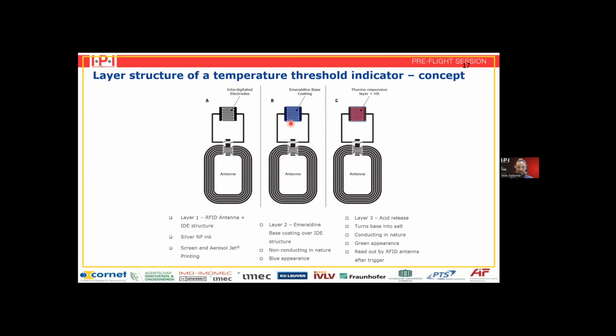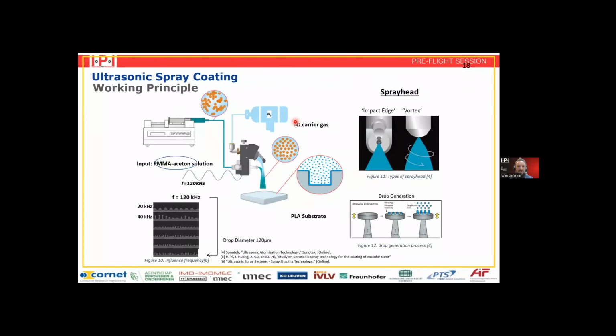And the coating itself is not screen printed, but is ultrasonically spray coated. That's a technology that we also have in the lab, besides screen printing and inkjet printing, for example. This ultrasonic spray coating, how does it work? Well, quickly, you have a syringe in which you have your ink, and the ink can be composed of some solvents with nanoparticles or with a polymer, can be very diverse. The ink formulation is much more, let's say, less stringent than with inkjet printing, because what happens is you bring